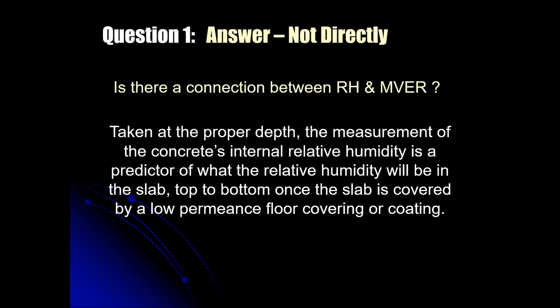And it's because of that that we, in 2001, adopted the European method of measuring relative humidity in the concrete. So taking the relative humidity at a proper depth is a predictor. The moisture vapor emission rate really isn't a predictor. And another reason that it's come into such question is because the calcium chloride pearls are actually hygroscopic. So they're drawing moisture to themselves that may not naturally be emitting from the concrete. But relative humidity testing is a predictor.